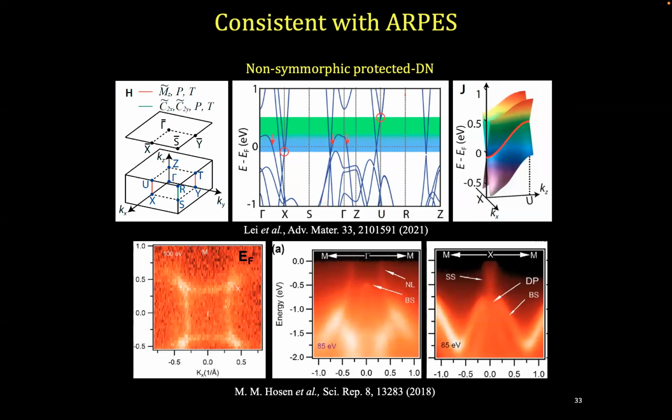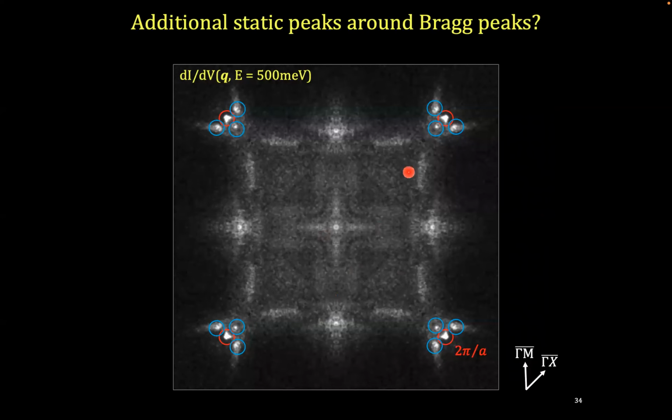And it just shows you that indeed we actually have the topological band structure in this system in our measurement. Okay, so this is the very first result. But I would like to direct your attention to the peak around the atomic lattice peak. These three blue things show up in our images, but when they show up, they don't disperse as a function of energy. That caught our attention, because when you see a peak, that means you have periodicity in the system. And in this case, they break the translational symmetry and they don't disperse.